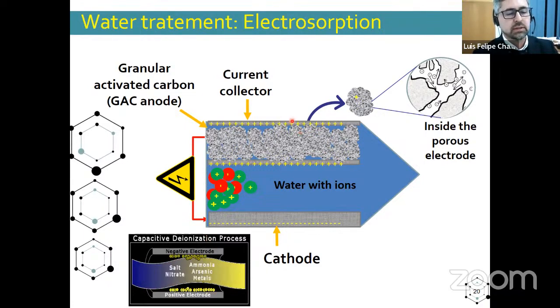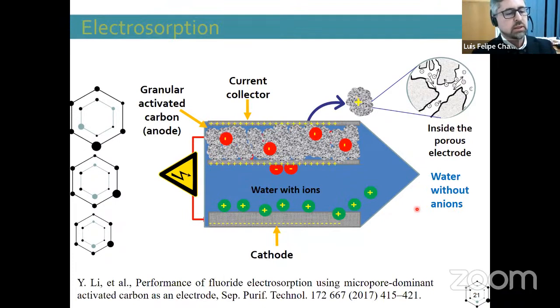Here, for example, this is an asymmetric cell where you can see the anode, and this is the cathode. This electrode is made with activated carbon, a granular activated carbon. And we can take advantage of the porous surface, as it was explained by René in the previous talk. So when you apply the potential, you can see that the ions are accumulated in the porous structure.